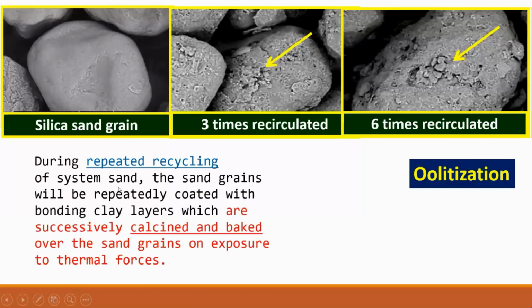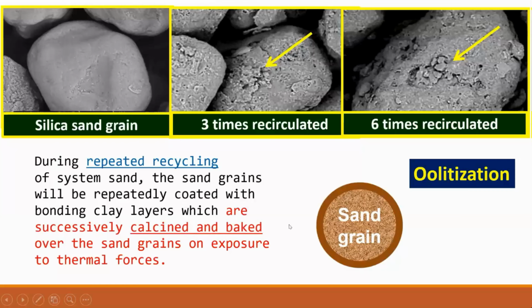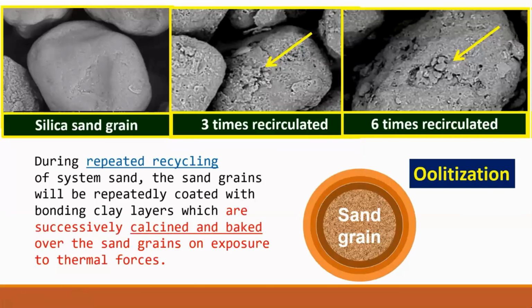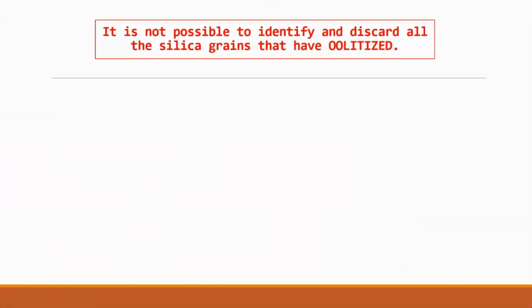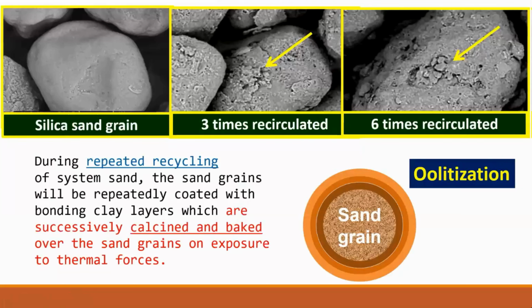So during repeated recycling of system sand, the sand grains will be repeatedly coated with bonding clay layers, which are successively calcined and baked over the sand grains on exposure to thermal forces. Thermal forces are coming from the liquid metal, which is very hot, and at that temperature, this bentonite gets calcined, that is burnt and baked over, that means it sits on the sand itself. Now how are they forming? From the sand grain, one layer, second layer, third layer, like that, they build up over and over, and then they become oolitized. So some time we have to do to remove these oolitics and then add fresh sand.